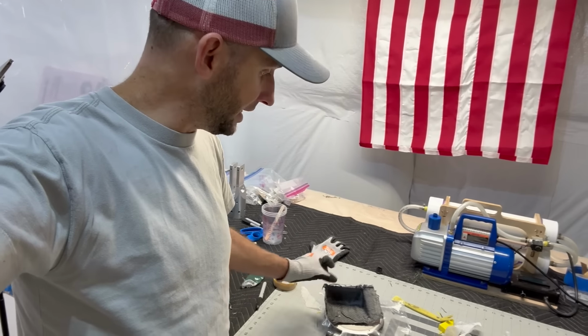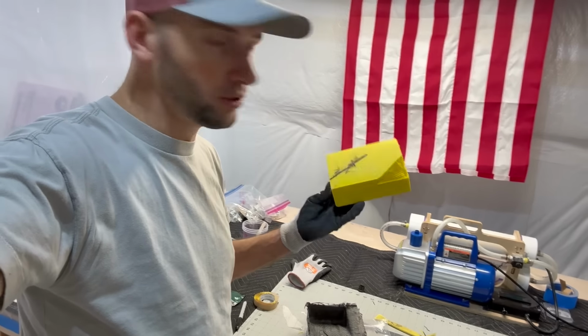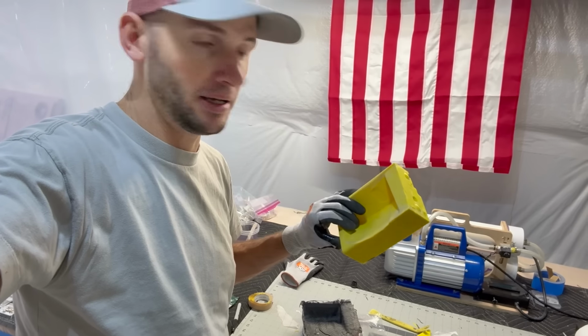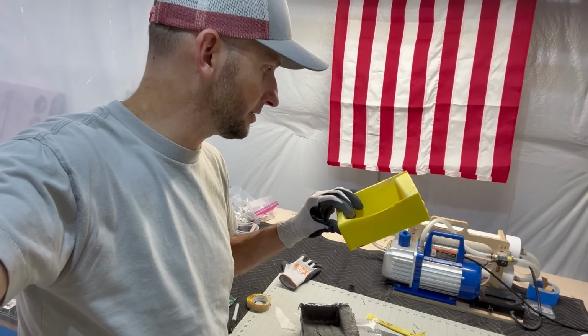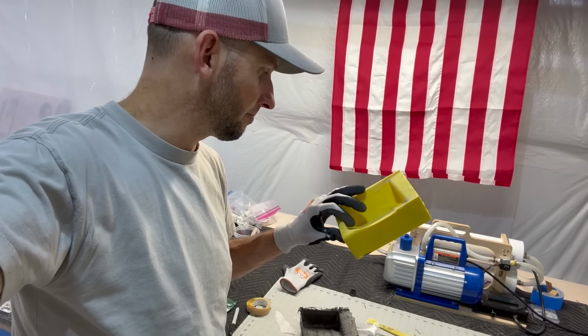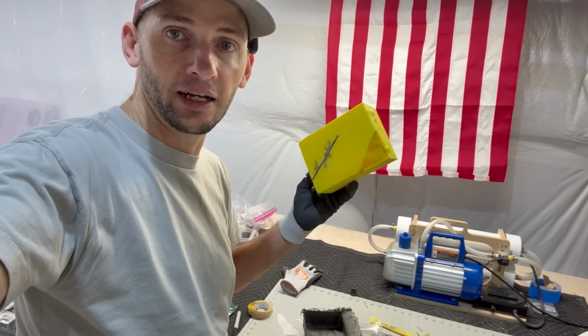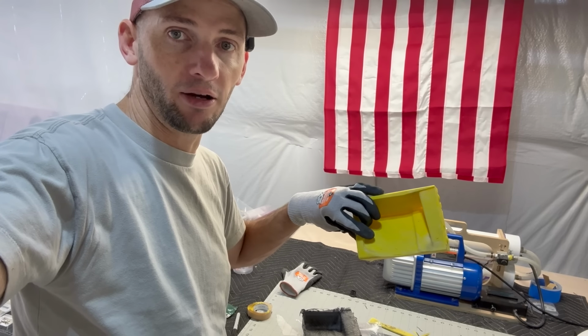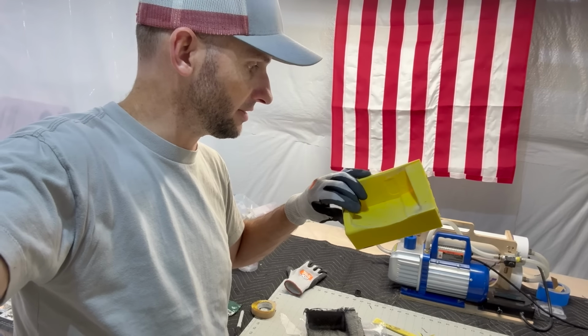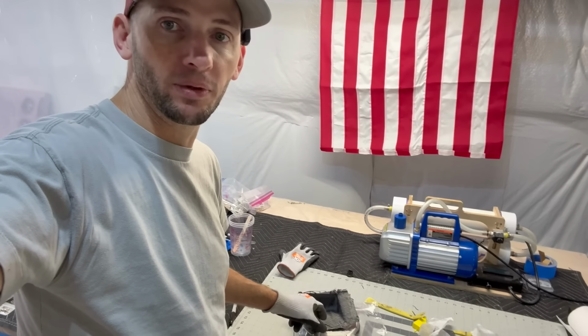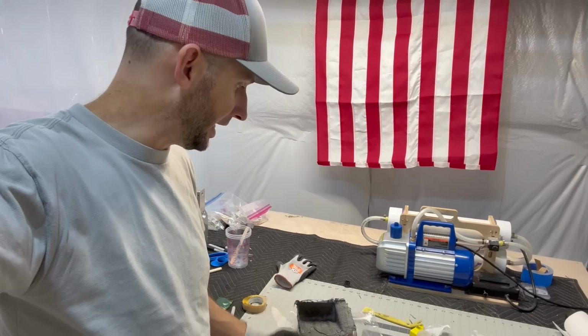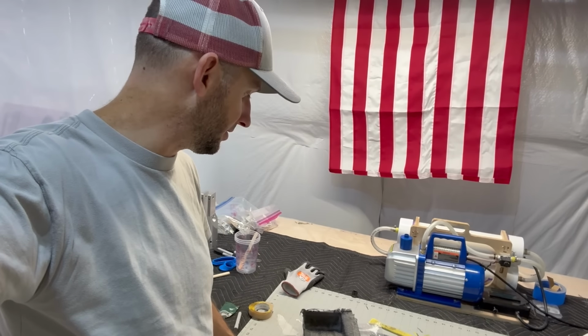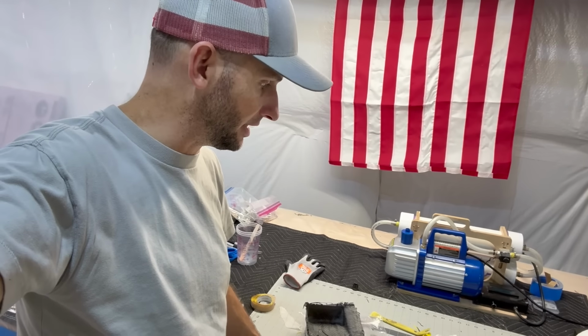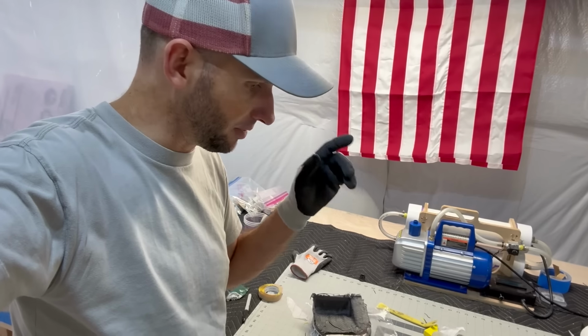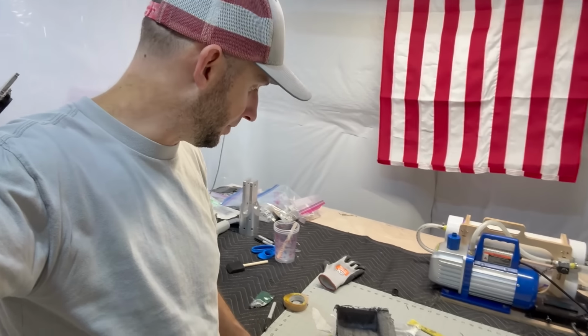My assumption is that the mold is porous, and as I pulled a vacuum on it, the air that was on the inside of this made its way out through the surface and went through the carbon and then into the peel ply, or into the breather, and it just sucked all the resin in it. I think most of the resin ended up in the breather and not in the part.